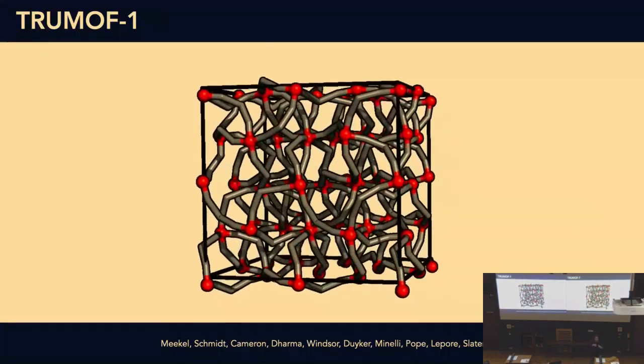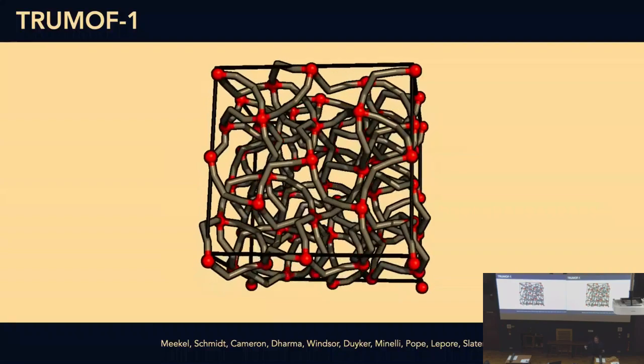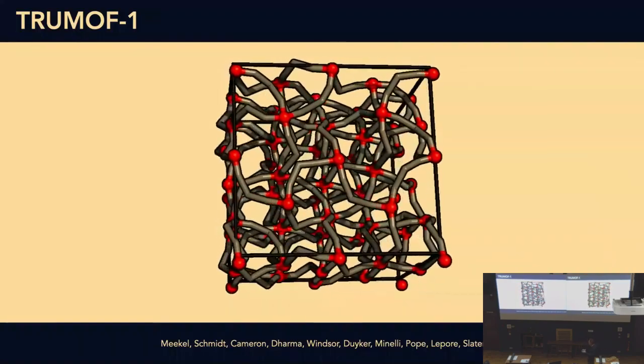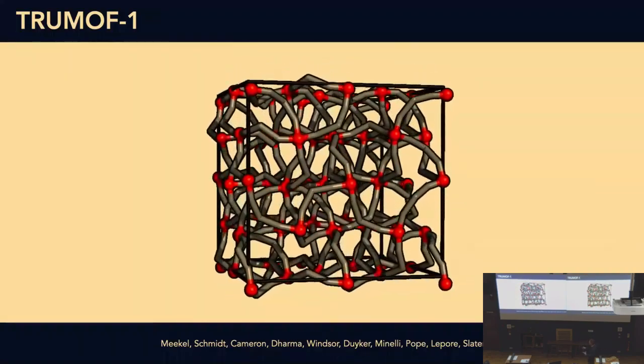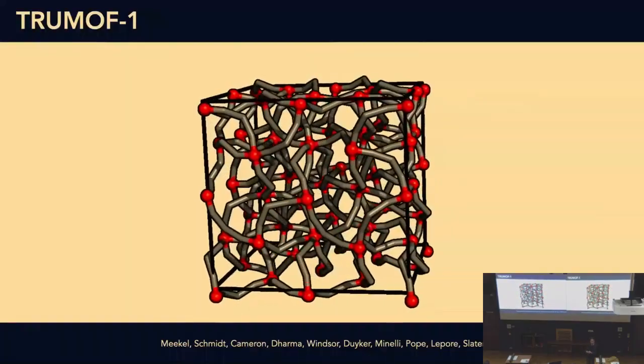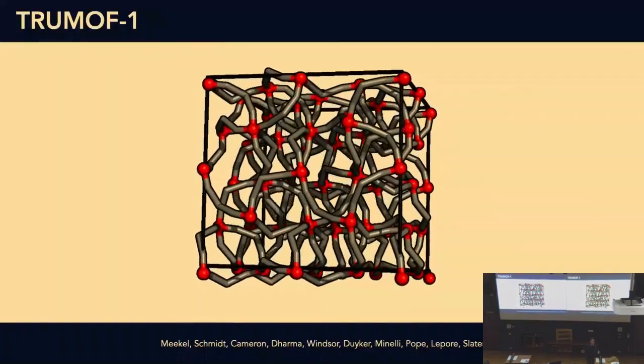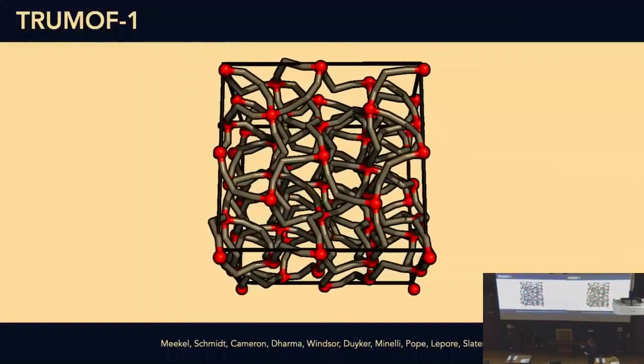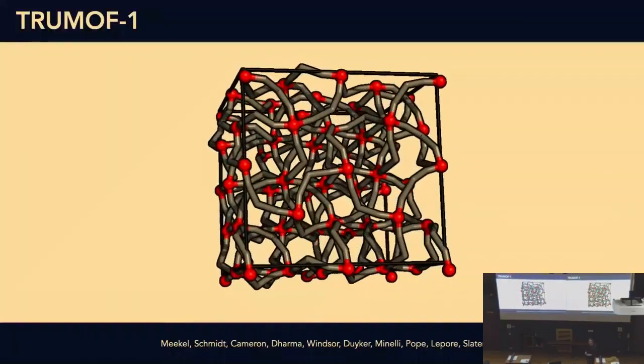It's based on a periodic arrangement of clusters, like a Truchet tiling. It's based on something periodic. So here the arrangement of these red spheres, the clusters, is actually periodic. They've all got the same local connectivity, but they connect up to form a network that never repeats. And the channels of these systems are entirely disordered, but in a non-random way.